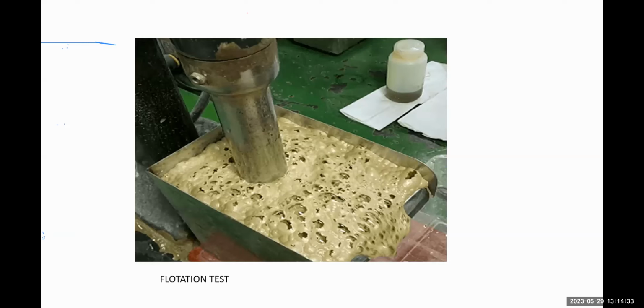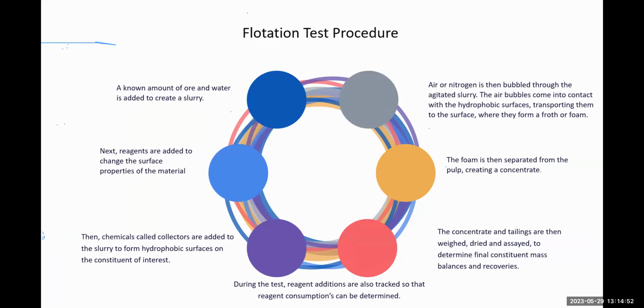Whatsoever you're scraping out contains the analyte of interest, which in this case is our lithium oxide, rather, not hydroxide. Hydroxide is gotten from the refining process. It's oxide that you get from the beneficiation. So all these things you are doing here, you are just trying to get oxide to concentrate it to 5 to 7% oxide. Next slide. Then we are almost done.